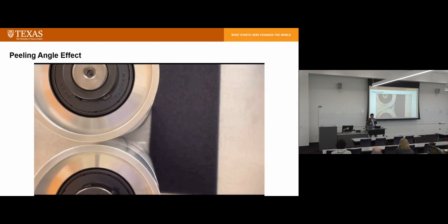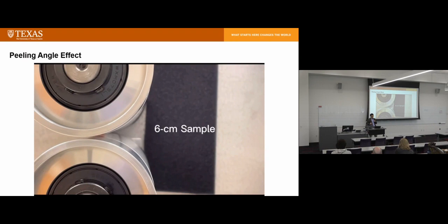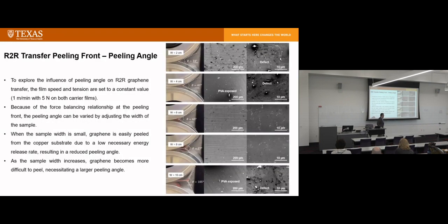This is the 2 centimeter sample. And this is a 6 centimeter sample. Because the width of the sample at the peeling front has changed, your peeling effort is going to change, right? So the 6 centimeter sample needs the peeling front to move to a certain location so that you satisfy the peeling condition, then the peeling can start. The reason for showing this is that during the experiment, we noticed the peeling angle will change. So we decided to study the peeling angle effect.